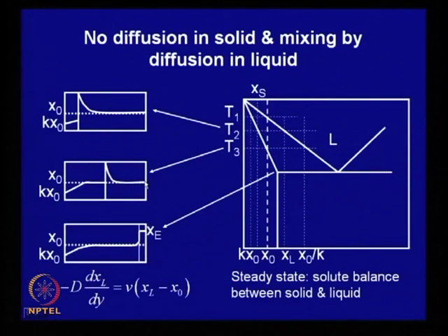This is the concentration profile in the liquid, and it proceeds further. Towards the end of the solidification, again there will be some transient, we assume. So, there will be a stage somewhere here where there is a balance and a steady state, and after it reaches the end, the liquid will again try to get enriched. Towards the end there will be a large difference in composition in the liquid, where the liquid will have a build-up, and here it may reach the eutectic composition.